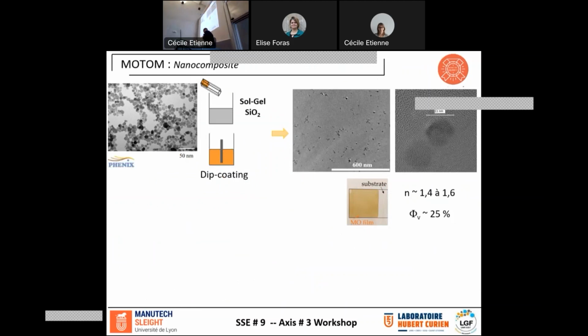This is what we are doing in the group. So this is a silica matrix with nanoparticles inside. It is done using magnetic nanoparticles. They are in liquids. You just add that to a sol-gel preparation, and through dip coating of the substrate in the solution, you can obtain that kind of film. So you can see the nanoparticles inside.